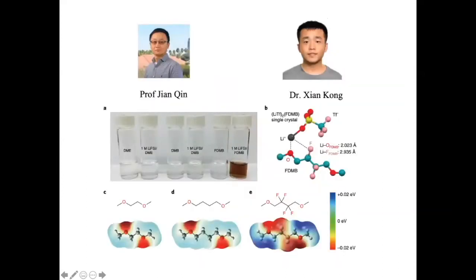So the further study, through simulation, indicates, if you look at FDMB, the color is actually brownish. Other electrolytes will be transparent. It turned out that the lithium coordination can coordinate not only with oxygen in the FDMB, but also with the fluorine. Through this molecular dynamics simulation, we are now figuring out, to some degree, how coordination happens in this electrolyte. So it's actually quite exciting. I encourage you to read about this, our new work that just came out a couple of weeks ago, on the discovery of a new type of solvent to form electrolyte, with one of the best performances discovered so far for lithium metal in the whole battery community.